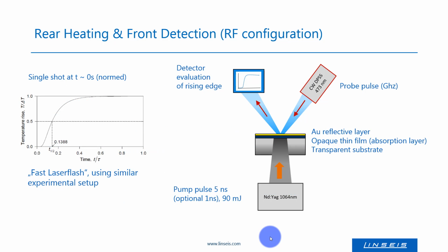So when we now use the classical laser flash setup and simply change the limiting components, we come to a configuration like this, which is called RF configuration. This is derived from rear heating and front detection, with a nanosecond pulse laser and a continuous wave detection laser in combination with a high-speed silicon photoreceiver.